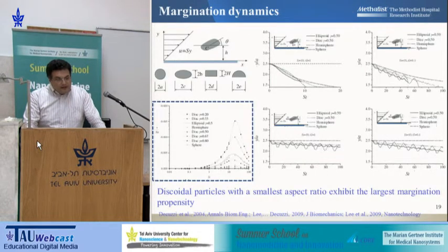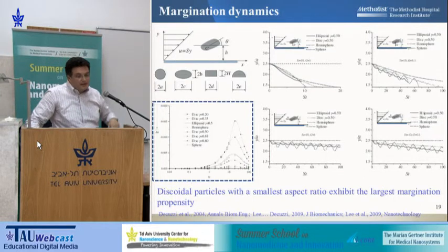Now, another important concept that I think we were the first somehow to introduce or justify was that of using non-spherical particles for targeting the vasculature. And this was, again, initiated through computational modeling. And we showed that if you start using non-spherical particles, you can actually have these particles drifting laterally across the vessels and tend to accumulate towards and move towards the vessel walls.